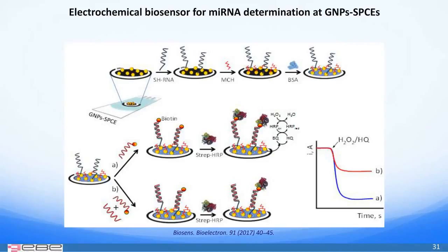The sequential assembly of mercaptohexanol ensured that the thiolated probe stands up and extends to the solution while minimizing non-specific adsorption. The biotinylated microRNA competed with the target microRNA for hybridization with the thiolated RNA immobilized, and labeling was made with a streptavidin HRP polymer. The analytical readout was obtained again amperometrically, in this case with the hydrogen peroxide hydroquinone system. The higher the concentration of the target microRNA, the lower the amperometric response measured, as a consequence of the smaller number of biotin microRNA molecules attached to the electrode.